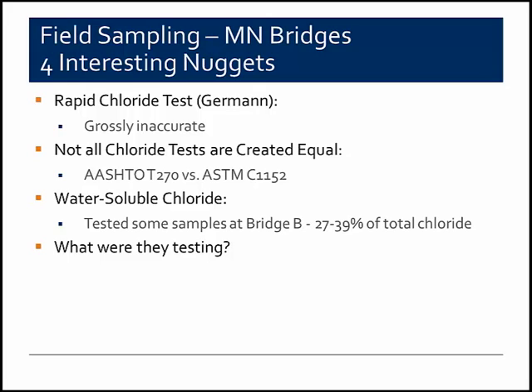And although the instrument is represented as being very accurate, what we found was that it was very inaccurate. Part of the issue may have been, at least initially, the time of sampling. We were collecting samples when it was extremely cold, and so some of the erroneous results were believed to be related to that. However, some changes were made to that process, and the RCT tests were run in hotel rooms at the end of each day, and we still found the same inaccuracies. And so unfortunately, that test just was not a reliable indicator of what sort of chloride content we would expect to get. So it was dropped from the program.